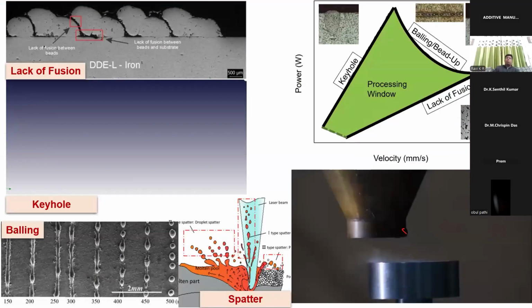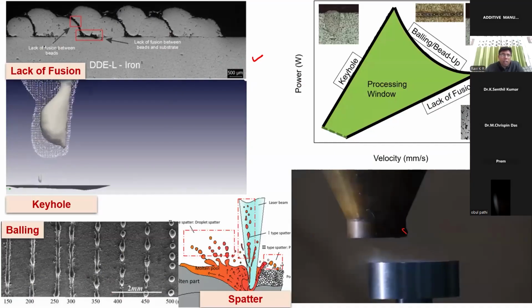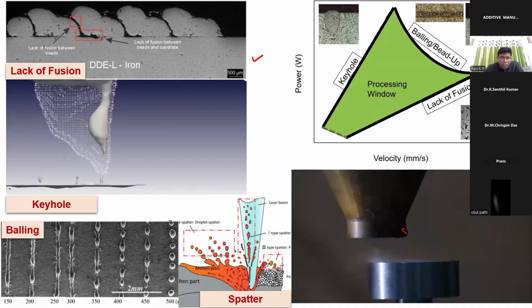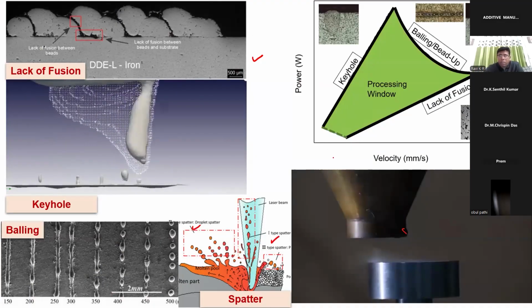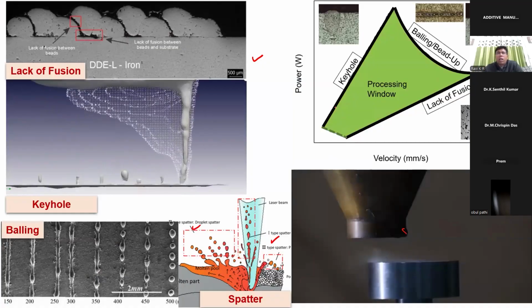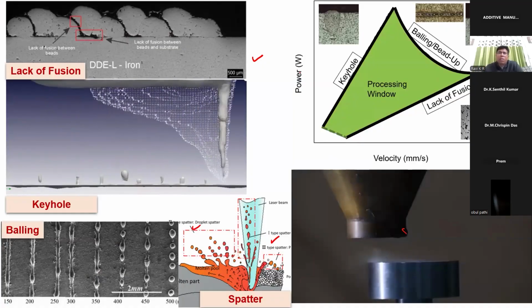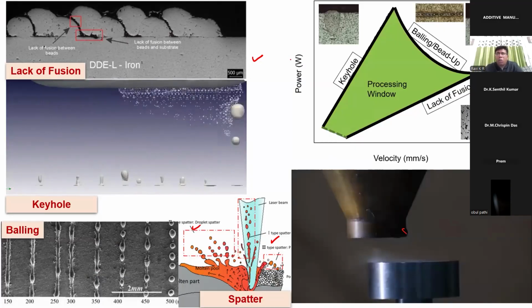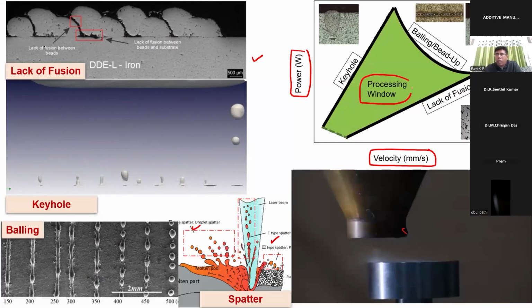Okay, now we'll come to this technique. What kind of defects will we be getting? Usually we get lack of fusion defects, keyhole defects, and we also get balling, and we also get spatters. To understand all these defects, as I told you, there are many parameters, but usually we control these two parameters, keeping all the other parameters constant. These are the two major parameters: one is the laser power and the other is the velocity at which we work. So usually you can get an optimum processing window for additive manufacturing.